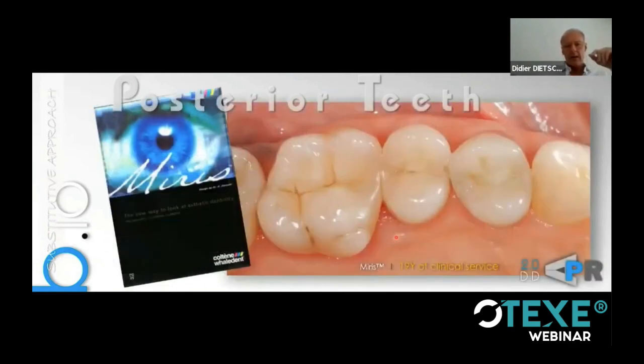That was done at the time of the launch of this product. So you can have the proof that I'm not lying about the longevity of those restorations. And now they are seen here nearly 20 years after placement. You see that the form, the anatomy has not changed. The adaptation remained absolutely correct for 20 years of clinical service, with minimum marginal degradation.